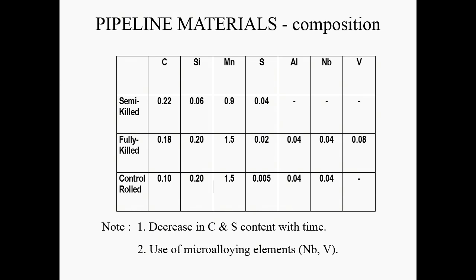Okay, we've gone for fully killed steels. Aluminium has been added, niobium and vanadium. Controlled rolled steels maybe don't need the vanadium because we've got the smaller grain size, so we can take that out. So the decrease in carbon and sulfur content with time has really driven the improvements in the properties of steels for pipelines at the grades up to X65, X70. And then when we go to higher grades, the use of microalloy elements has also been very important.